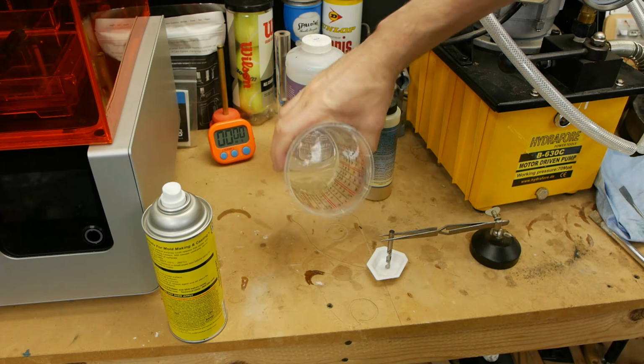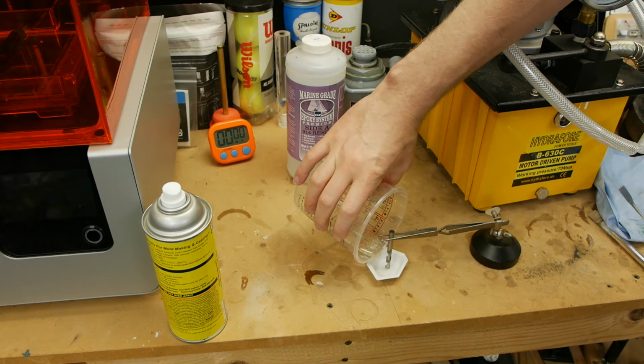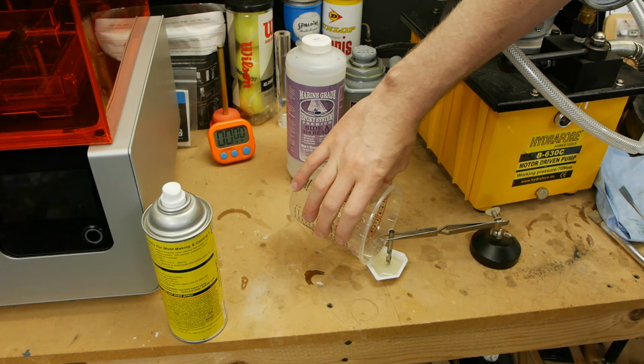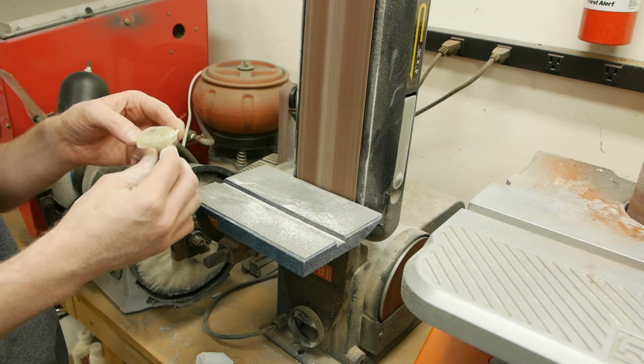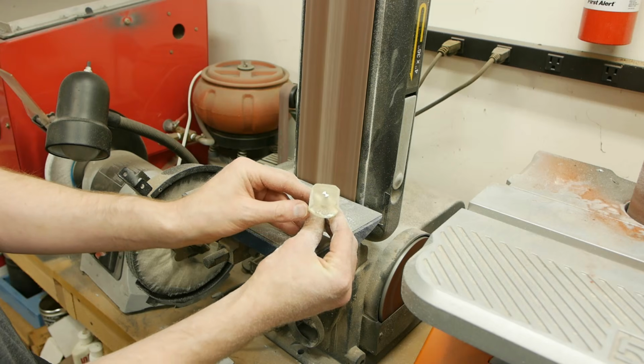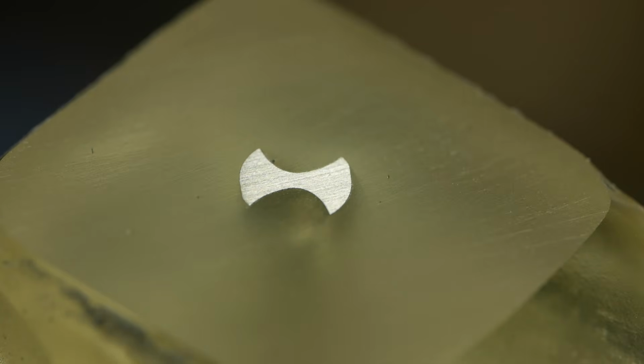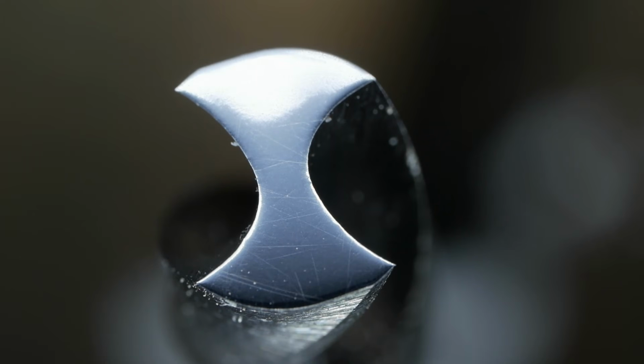So I made my samples by putting them into a little tub with some epoxy, sanding it down, and then going up through the grits all the way to these really fine polishing papers. It's actually a cloth coated with really fine abrasive, like 0.5 micron abrasive or something. And you end up with this mirror finish, crazy polished kind of thing.